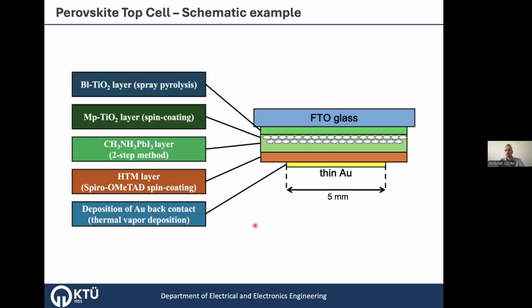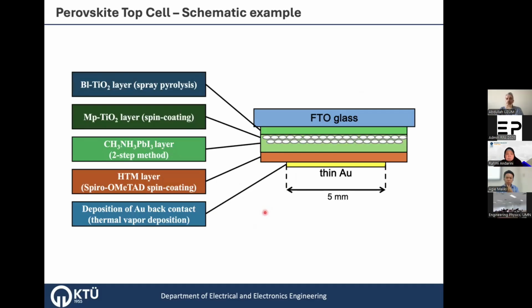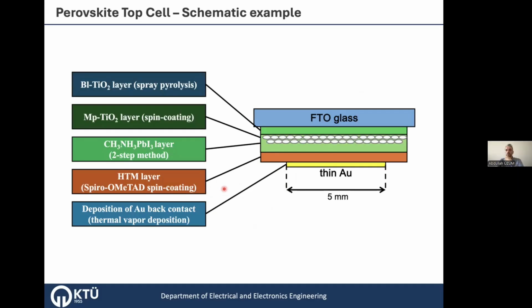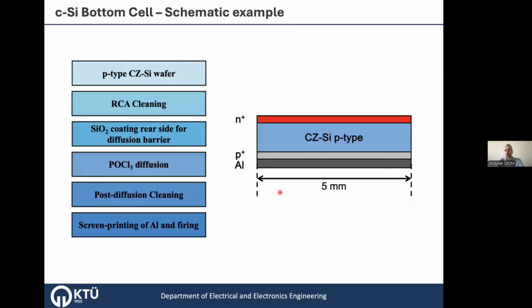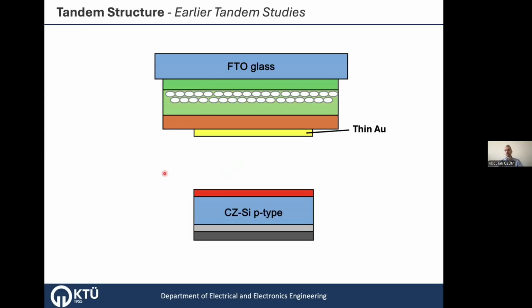First, at that time, we used the simple mesoscopic structure of the perovskite solar cell, with titanium dioxide as the electron transfer layer, methylammonium lead iodide as the absorber layer, and spiro-OMeTAD as the hole transfer layer, and a thin gold back contact. And for the bottom cell, we prepared at that time a simple full back surface field solar cell without front contact. This is one of the first studies of tandem solar cells, that's why I guess it is important. First, we made a very thin layer on the perovskite layer, about 2 nanometers, 1.5 or something. And then we sputtered ITO on that and optimized it seriously.